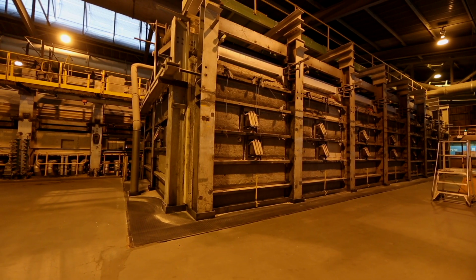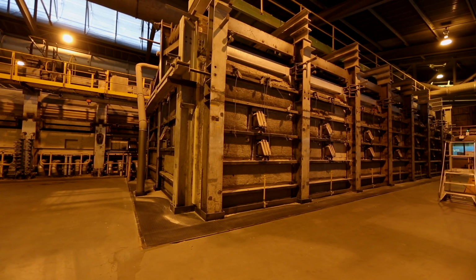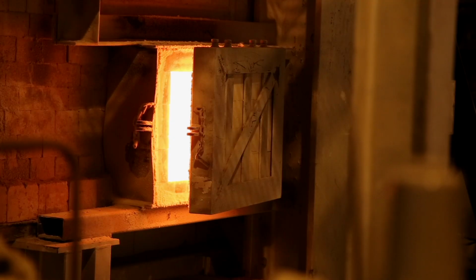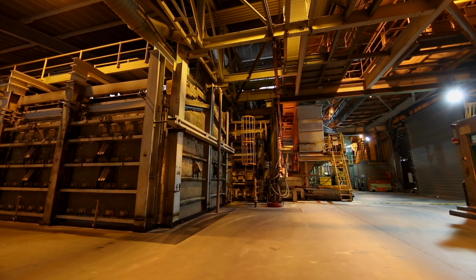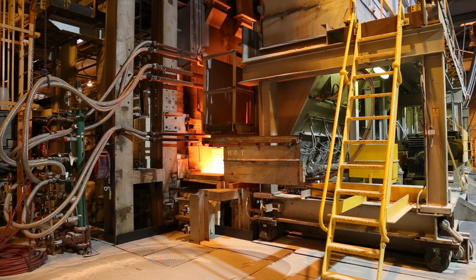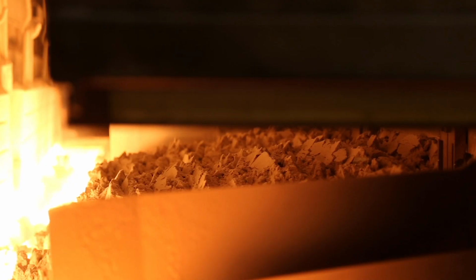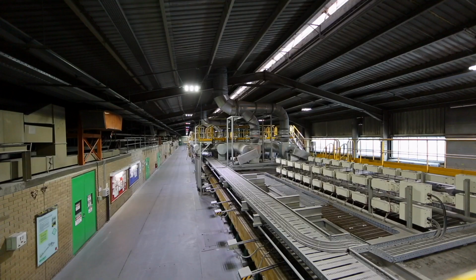And it's this continuous burning of the furnaces that not only makes for an incredibly expensive operation, but like all float glass factories around the world, it takes an enormous physical toll on the kilns. So this production line must be totally rebuilt every 15 to 20 years at a cost of around $50 million. Around that period we do close it down, shut it down, and then actually repair the furnace. So we go cold for about 3 months, repair all the factories, mainly in the furnace, and then restart the furnace in a controlled fashion to get the temperatures back.